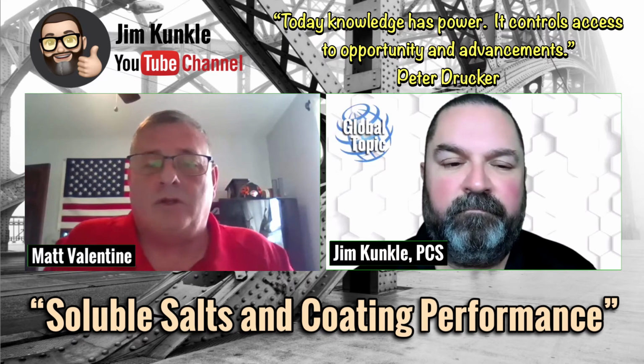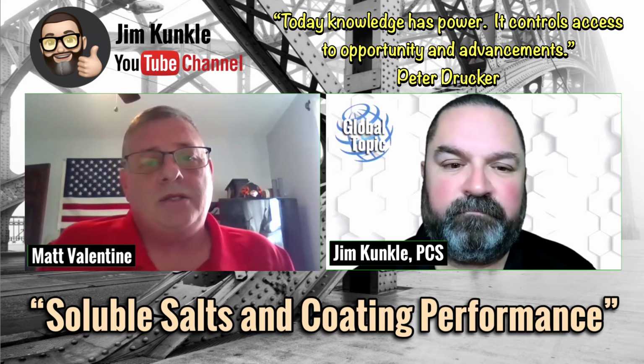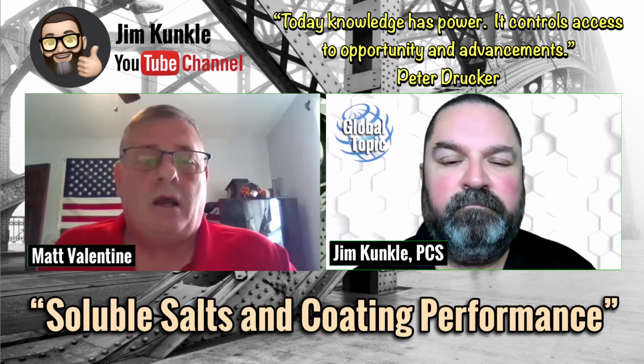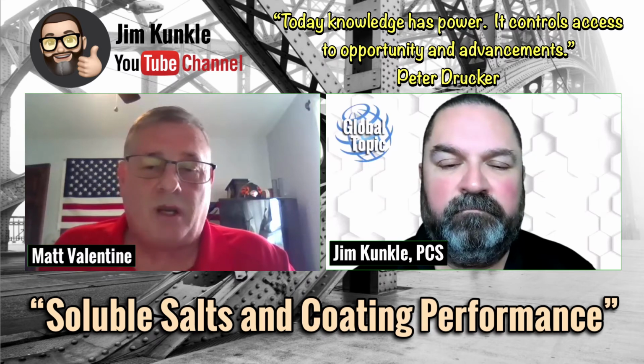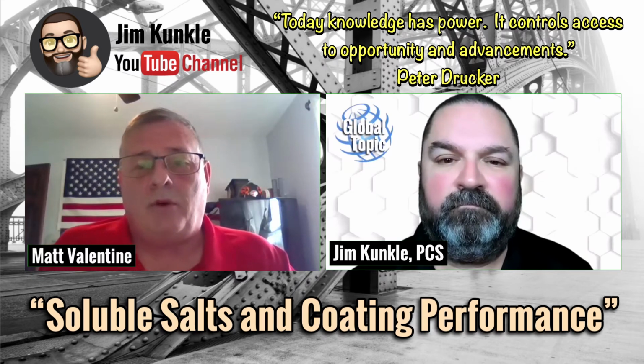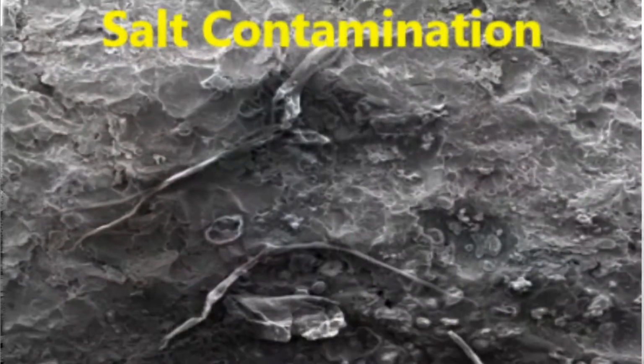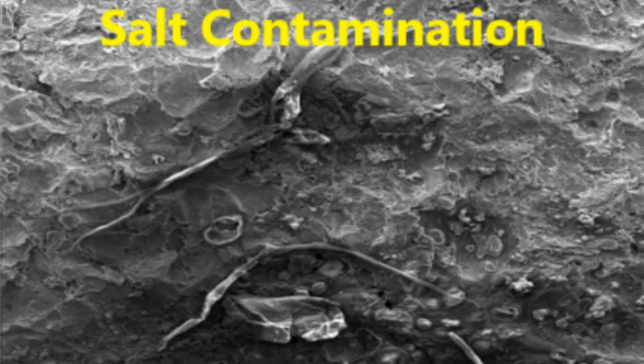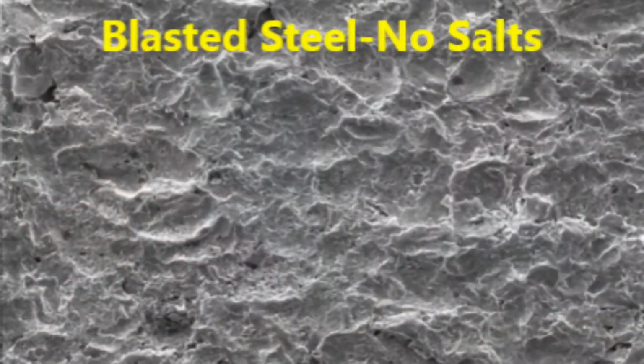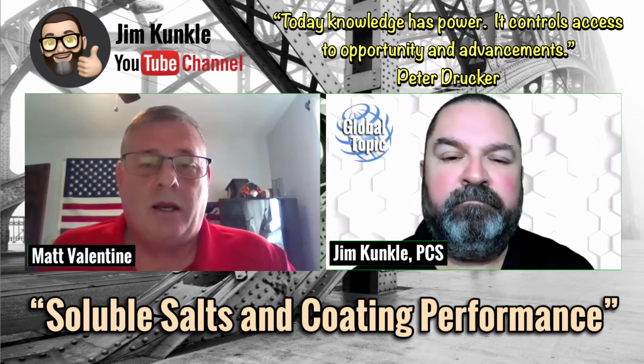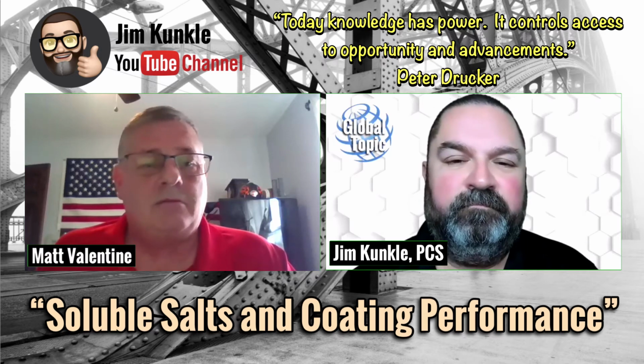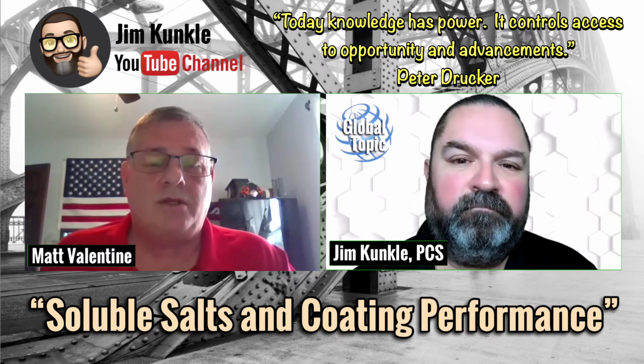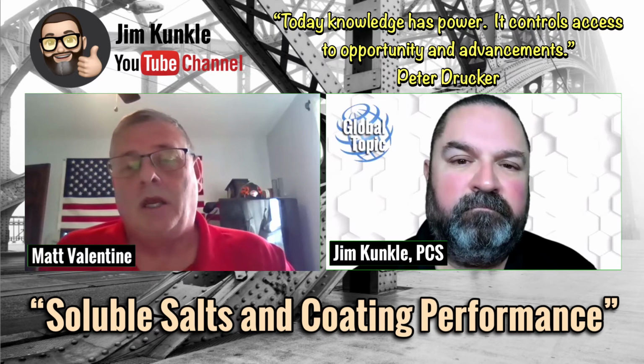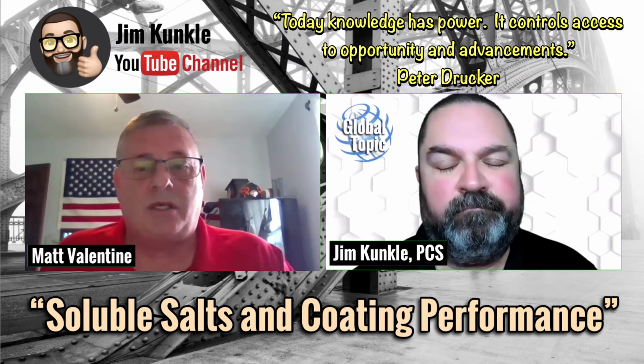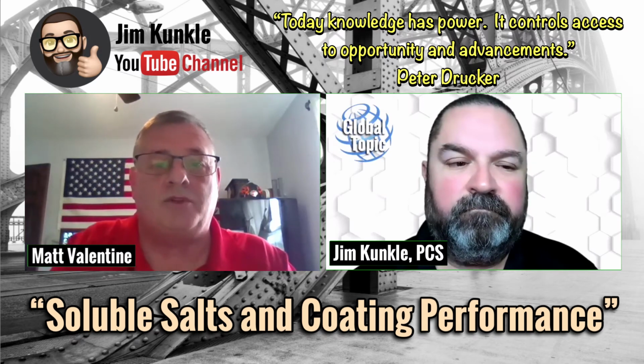So you've determined you have salts. What you do then is you come with a 1% solution. You can go as high as 2%. We've had some customers even go higher than that. You mix it with a pressure washer, 2,500 to 3,500 PSI, and you pressure wash the entire surface to remove the salts. One of the challenges is that you're dealing with a lot of salt, so you have to retest afterwards. That product being slightly acidic will always flash rust the substrate. So once you've retested and determined that the salts are gone, you'll sweep blast the steel and then coat your substrate.